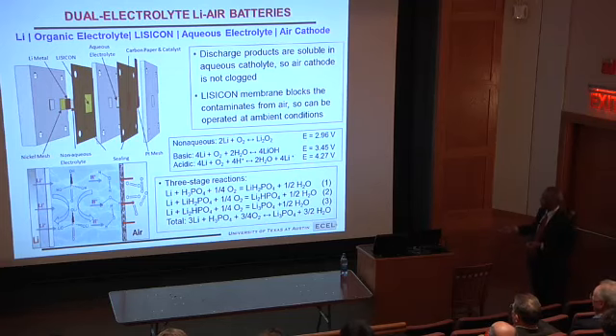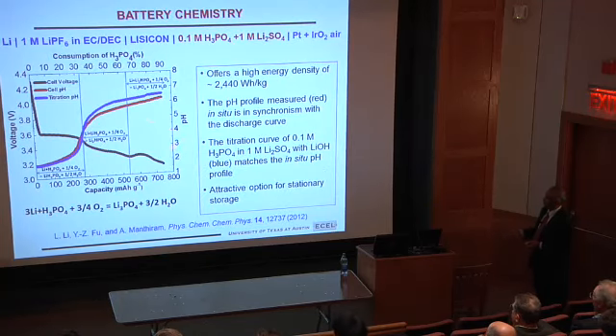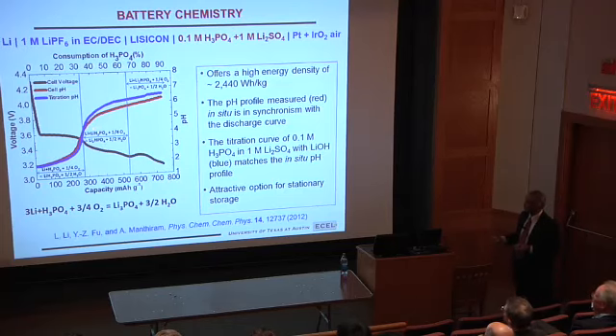So we are playing with that kind of system with phosphoric acid. Phosphoric acid can transfer 3 protons. So we wanted to do nice chemistry. That's a discharge profile. The phosphoric acid can also be a flow system. One side lithium not flowing. The other side cathode can be a flow-through system. So we monitor the pH in situ. We can demonstrate the cell chemistry, because when you consume phosphoric acid to form lithium phosphate, pH should increase. And that's what you see here from this pH plot.